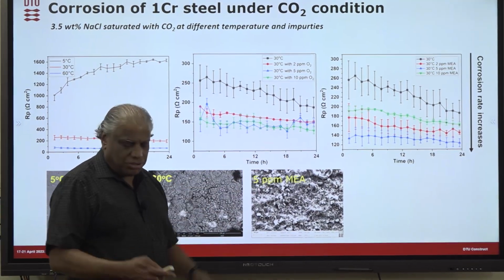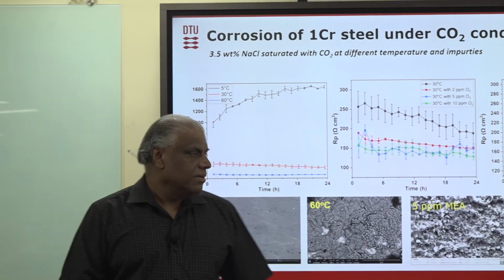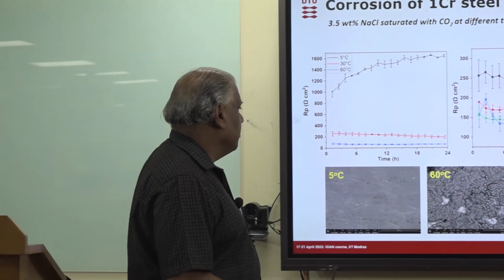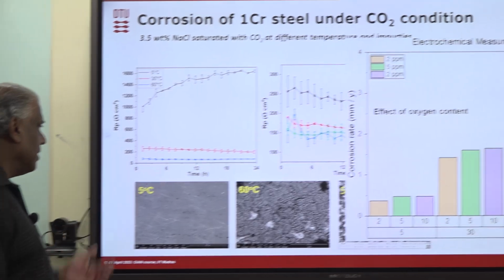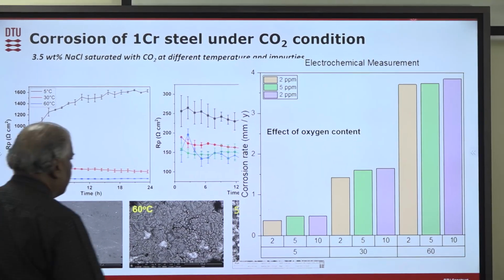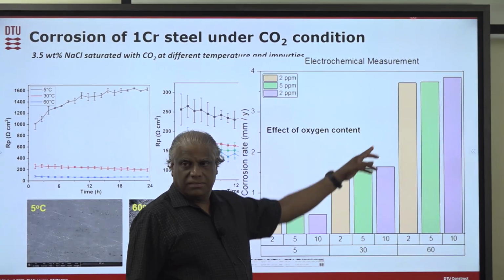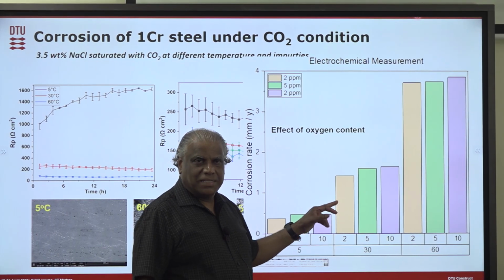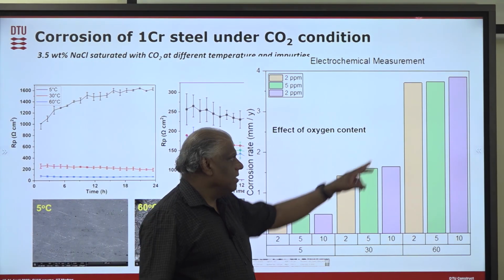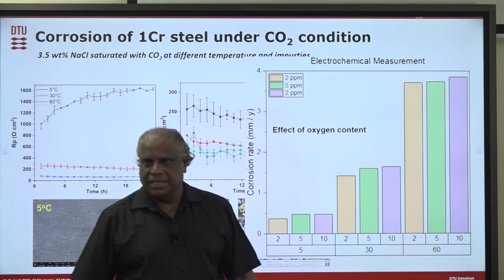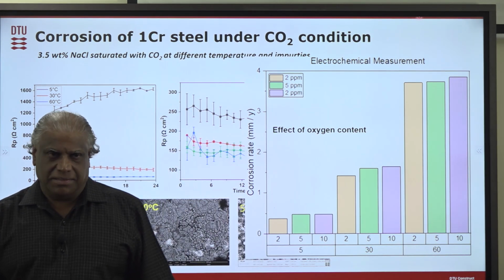Just to show a glimpse of this, like this oxygen content as an example, but you can see the temperature has a very, very clear effect. So we should expect that from the top of the well to the bottom of the well, there is a very high difference in the corrosion rate because of this when they inject.